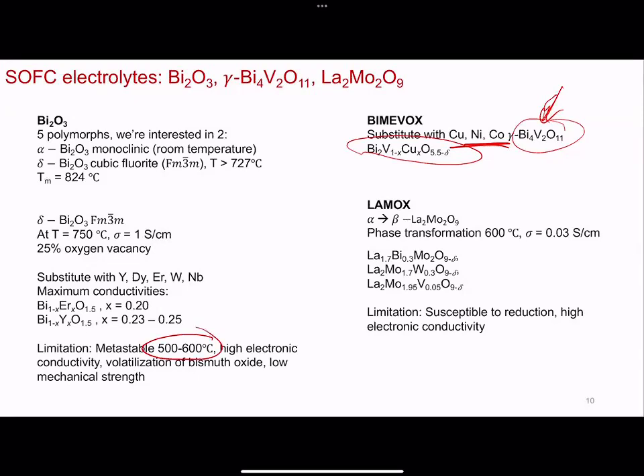And then the reverse also is a problem, which is you can get high ion conductivity at a lower temperature, but if you want to use these solid oxide fuel cell electrolytes at 500, 600 C, some of the components start to volatilize. So in the example of the bismuth oxide compounds, bismuth can start coming out of the oxide, and then you have decompositions of sorts. So anyway, that's all to say YSZ and GDC are not the only compounds being looked at. There are some promising substitutes, other alternative options, but there are quite a number of challenges that these compounds have to overcome to be viable options as solid electrolytes.